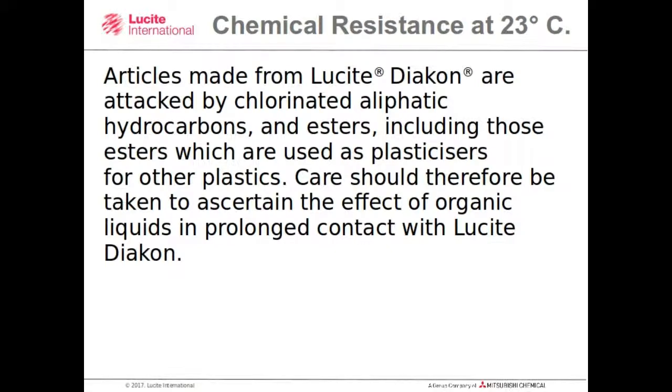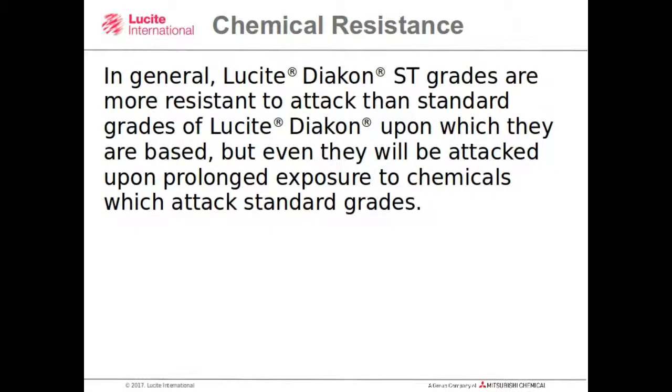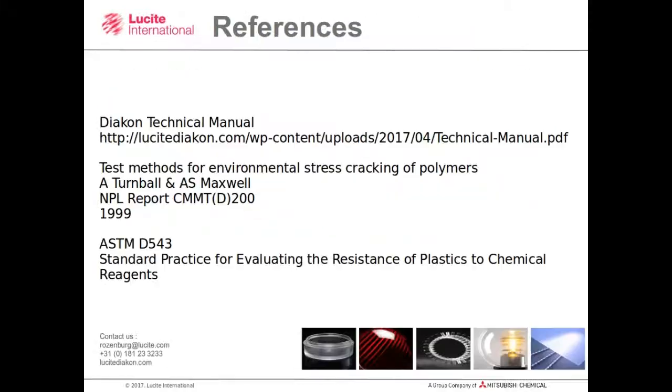Articles made from Lucite Diakon are attacked by chlorinated aliphatic hydrocarbons and esters, including those esters which are used as plasticizers for other plastics. Care should therefore be taken to ascertain the effect of organic liquids in prolonged contact with Lucite Diakon. In general, Lucite Diakon ST grades are more resistant to attack than standard grades of Lucite Diakon upon which they are based, but even they will be attacked upon prolonged exposure to chemicals which attack standard grades.